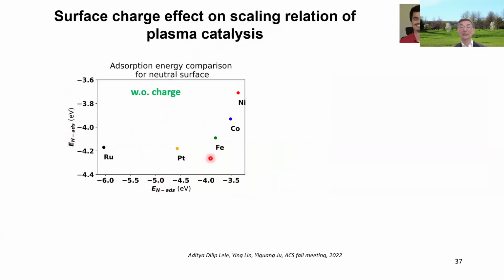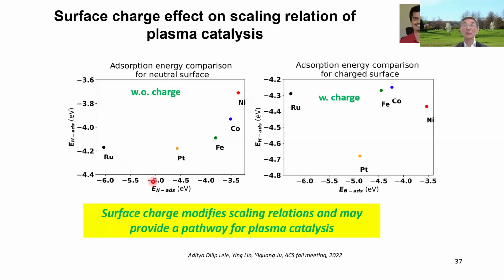So this is thermal catalysis. You can see there's a beautiful correlation between ruthenium, platinum, iron, and cobalt, and the adsorption and dissociation energy. What if you have surface charge? The DFT calculation shows a completely different story. This is the correlation between ruthenium, platinum, iron, cobalt, completely different from thermal catalysis.